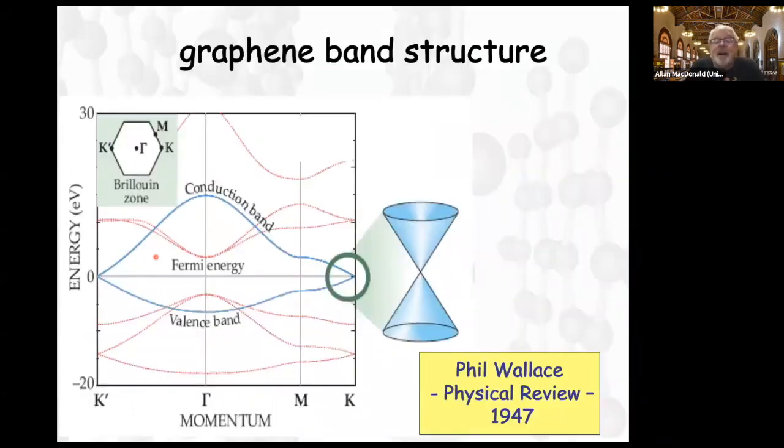So this is the band structure of a single graphene sheet. The relevant low energy states are the pi orbitals, odd under inversion in the graphene plane, blue on this energy versus momentum plot. You see it satisfies my criteria for a host for a Moire material in that its low energy states are in narrow regions of momentum space, actually near two points in momentum space that are related by time reversal, these inequivalent Brillouin zone corner points.